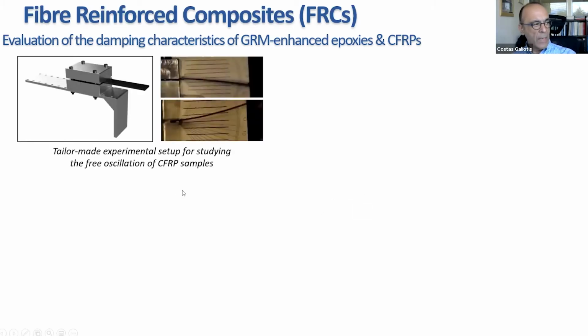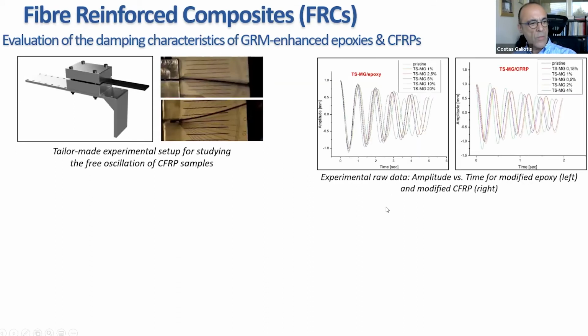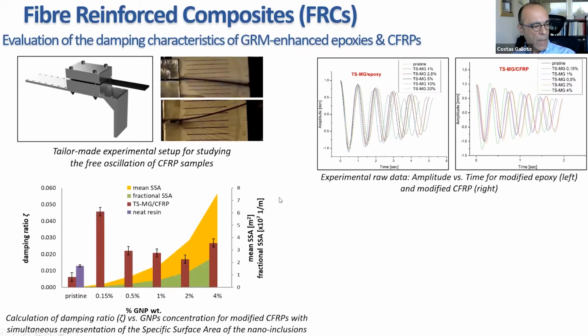And the same thing we have discovered when we look at damping characteristics. It's another problem with this brittle and stiff lightweight structure with carbon fiber composites. The damping is not very good. And we have some tailor-made experiments on the vibration properties of these structures. And you will see with small percentage of graphene, the whole amplitude versus time curves are affected quite considerably. And here you will see the pristine damping of the carbon fiber material. You will see that the carbon fiber is much less than the neat resin. So when you build a carbon fiber, then the damping becomes much worse.